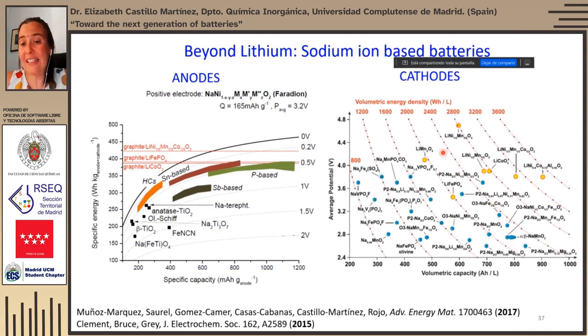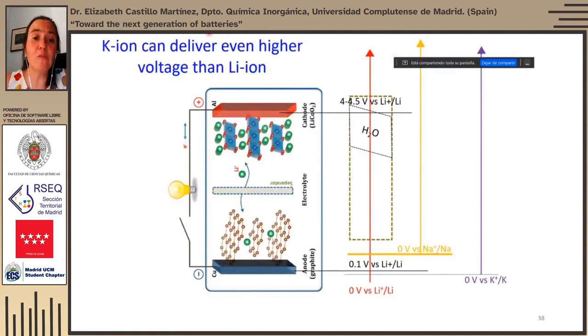But it is the layer oxide that have the highest volumetric energy density, and the hard carbons has the highest energy. If we move from sodium to potassium, we can see that potassium ion does plate at voltages which are even below lithium plating, and therefore, in principle, one could even achieve voltages higher than those of lithium batteries.